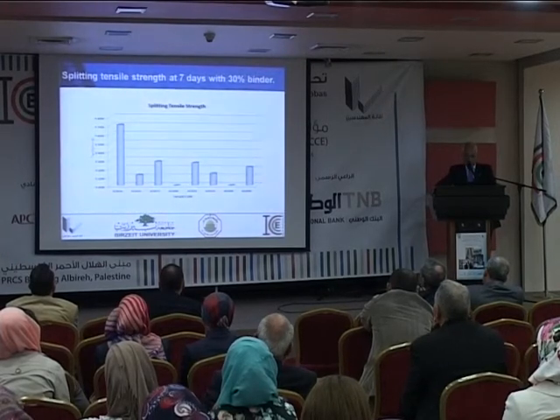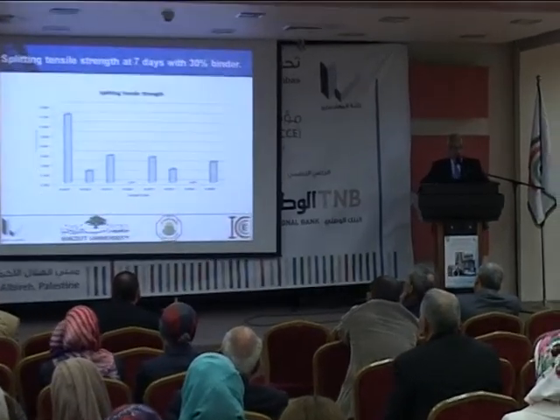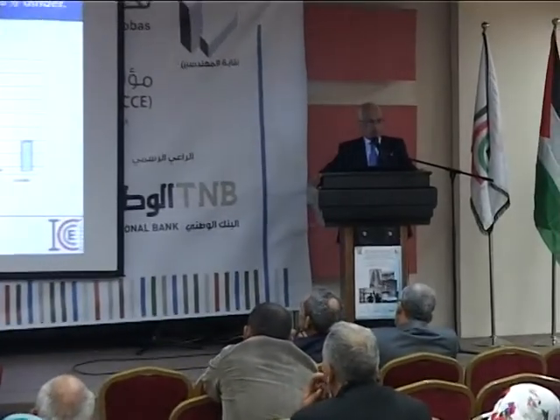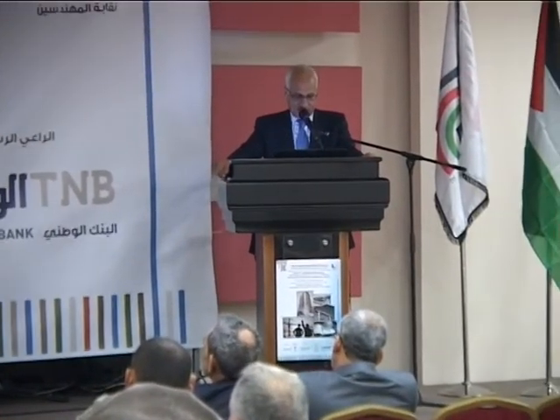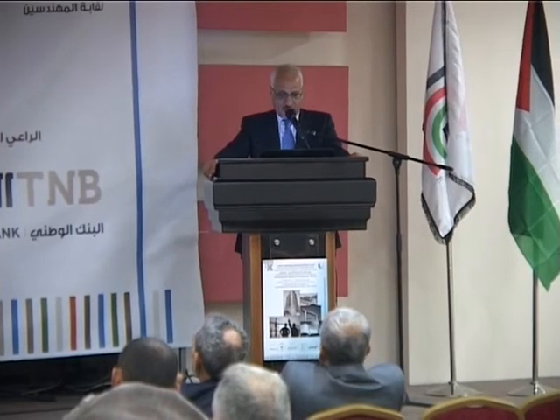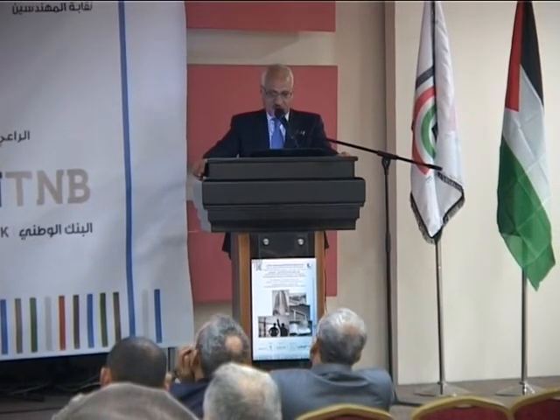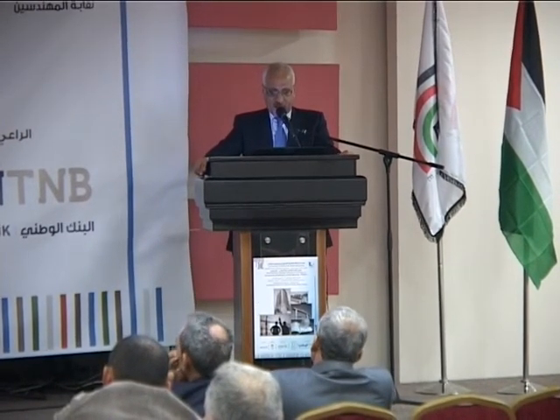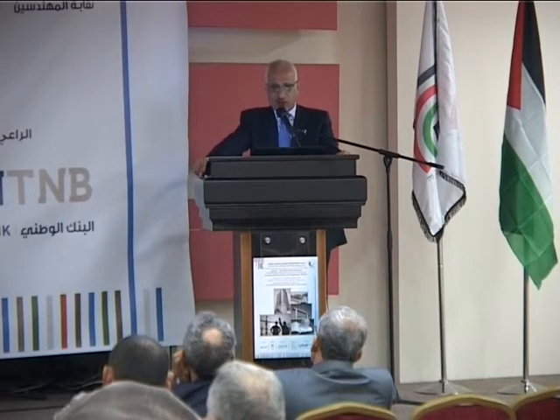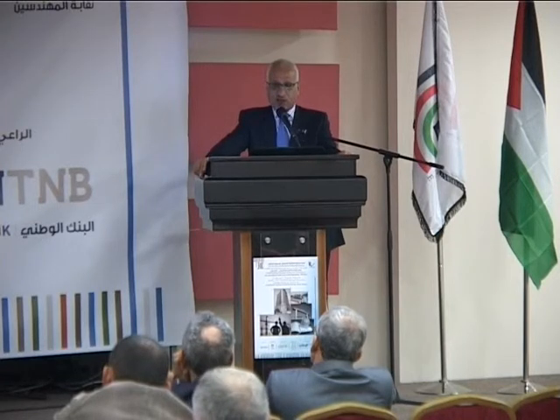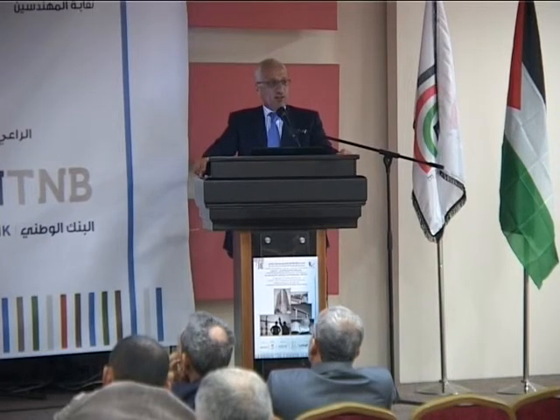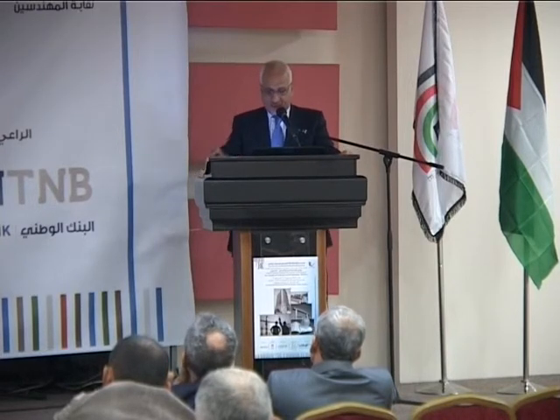figures for the splitting test and the samples with the highest cement, of course, performed very well and gave very high values. But if you look at samples number 3, number 5, and the last one, it shows that they achieved reasonable strength, because in blocks you don't need very high strength. A 2 Newton per millimeter squared block can give you results. So if one works more on this, we can actually achieve a reasonable product.